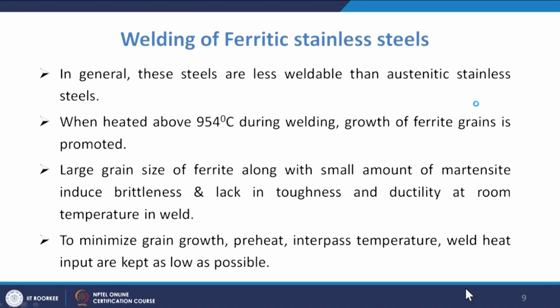So welding of the ferritic stainless steel, in general, those steels are less weldable than the austenitic stainless steel when heated above 954 degrees centigrade during the welding, and growth of the ferrite grains is promoted. Okay, the larger grain size of the ferrite along with a small amount of martensite induces brittleness and lack of toughness and ductility at room temperature in the weld. To minimize the grain growth, the preheating and interpass temperatures and weld heat input are kept as low as possible.